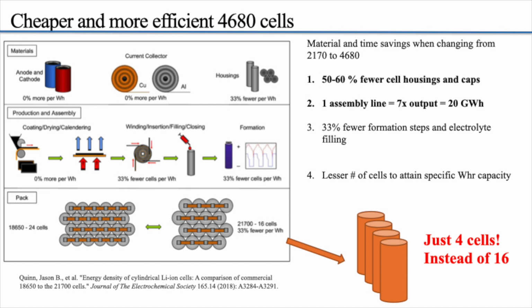So this is from a great paper where they compare 18650 and 21700. Now the amount of anode and cathode material is still going to be the same. It is the same for 4680 as well. But going from 18650 to 2170, they saw a 33% reduction in cell housings, the cell outer shell, the top cap, bottom cap, all of that. Now, going from 2170 to 4680, I'm expecting like 50 to 60% less cell housings and caps.